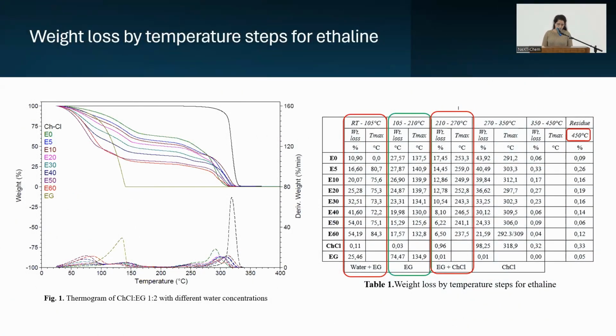In the first thermogram, we have 3 steps for the ethylene glycol solvent. In the first step, from room temperature to 105 degrees Celsius, the water has evaporated, has left the system, and also traces of ethylene glycol. In the second range, ethylene glycol has started to leave the system through intermediate acids such as glycolic acid and formic acid. In the third step, ethylene glycol fully leaves the system and choline chloride starts also to degrade. As we can see in the residue column, all the solvents were fully degraded.